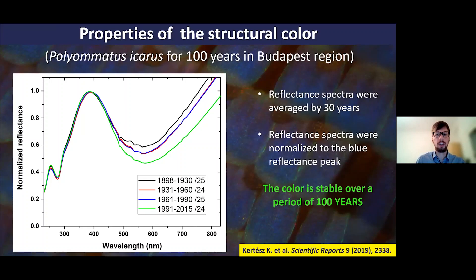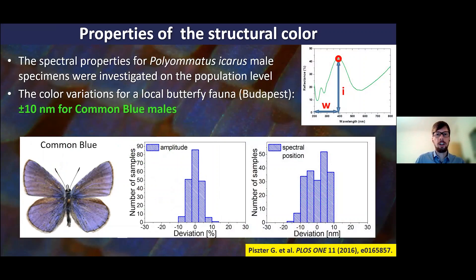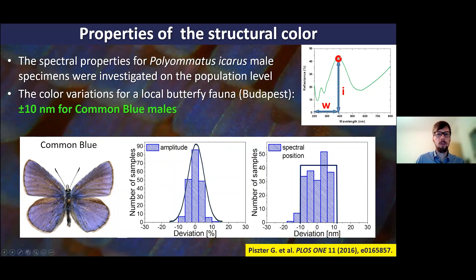The male common blue butterfly has a blue structural color on its dorsal wing surface that is important for its life and has been under strong evolutionary pressure. Under optical microscope the wing scales are arranged like tiles on a roof. Scanning electron microscopy reveals a sponge-like chitin matrix with embedded air holes — a three-dimensional photonic nanostructure — which is the source of the blue coloration. In cross-section under transmission electron microscopy, this is a multi-layer-like but somewhat amorphous structure with alternating chitin-rich and air-rich layers. Spectrophotometry gives reflectance spectra with a main peak between UV and blue around 400nm. Testing temporal stability using museum specimens from the last 100 years averaged by 30-year periods showed the structural color is stable over 100 years; differences are only seen in melanin reflectance due to photo-degradation of that pigment. Natural local population variability in the blue peak wavelength maximum is approximately plus or minus 10 nanometers.